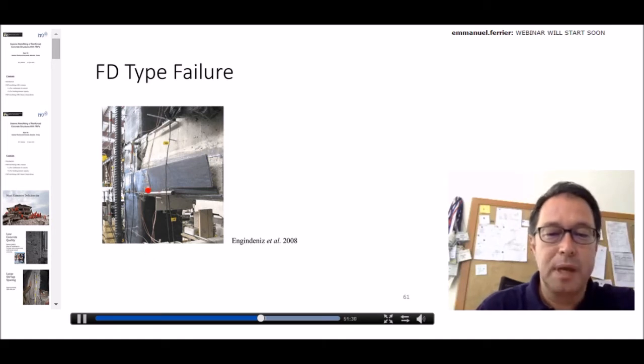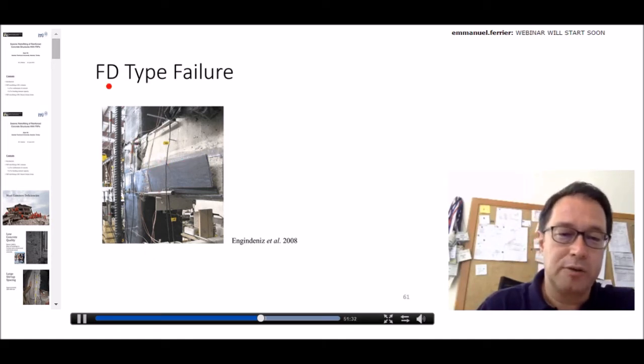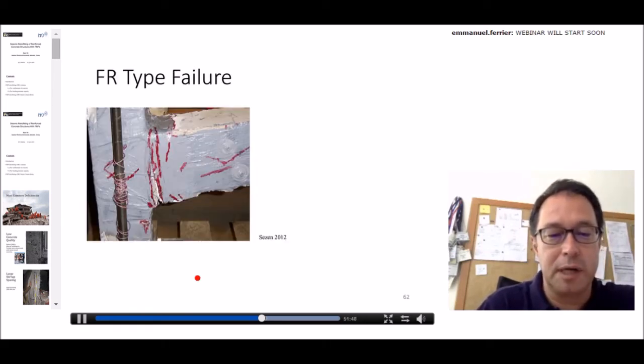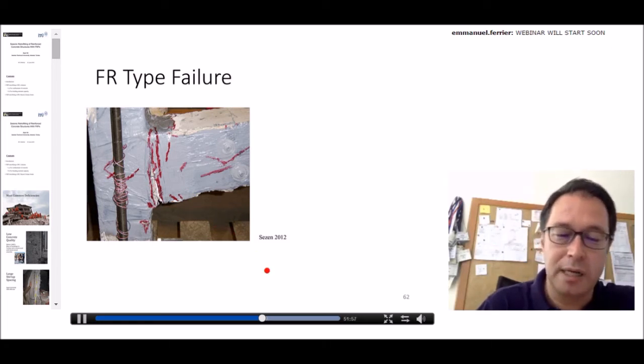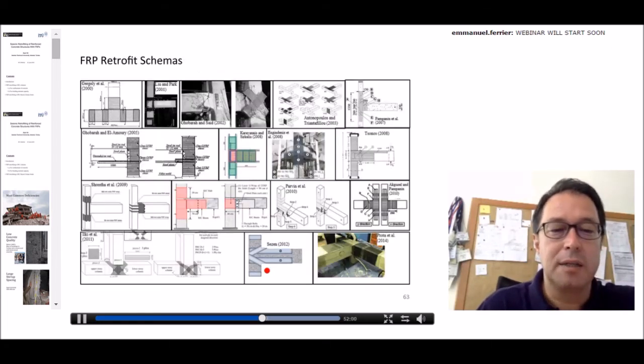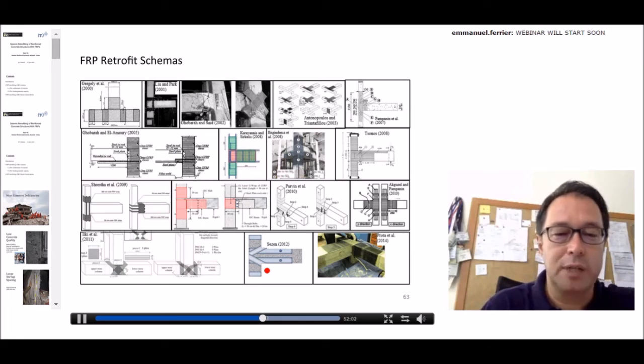This is showing a debonding case, FRP debonding. It of course depends on at which level this debonding occurs. If it happens very early, then it is not that meaningful. If it occurs later at a large drift, then this could be acceptable. And that's showing a rupture of FRP on the joint zone. Again, it depends on the design, and on the drift at which the failure occurred.